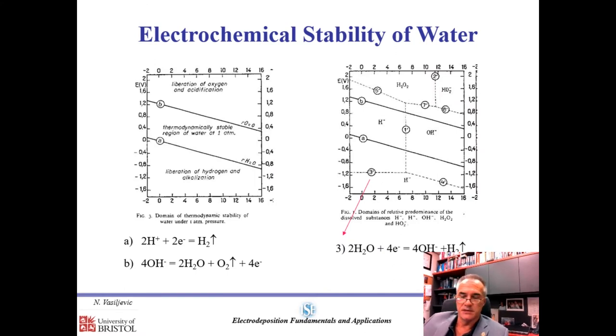Going further, when we discuss the magnitudes of the current densities, one thing that we should keep in mind is that there are certain limits to what type of current density will drive your electrode in what kind of potential regime. For that reason, the stability regime of water is commonly defined by these two reactions, which are hydrogen evolution and oxygen evolution. You should also keep in mind that as much as you have a reaction on your cathode, you also have the same type of processes in the opposite direction going on at the anode. So if you typically deposit metals on the cathode, you will most likely have some oxygen evolution on the anode side.